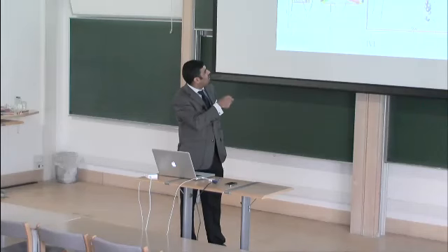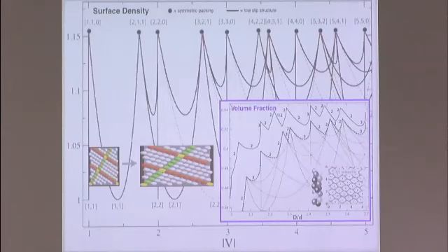We can compare this to the numerical results, unwrap those structures as I showed you earlier on, and ask what the direction of the line slip is. Is it direction 1, 2, or 3, and compare directly. For example, in this region and this region, which corresponds to this segment of curve, we are successful. We've predicted a line slip of type 2. Here again, we're successful, type 2. Here, let me pick this one instead, that's better. Here we predict a type 3, but we actually see type 2 for a long time, and then type 3 takes over. You'd think, where does this discrepancy come from?